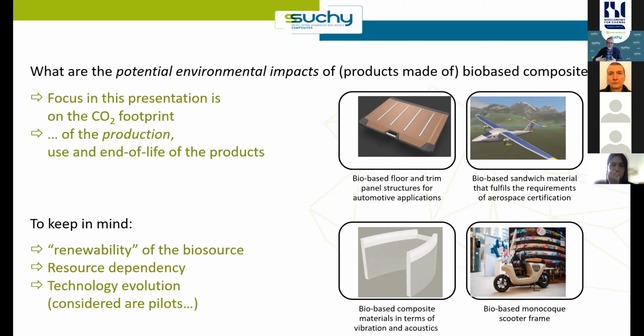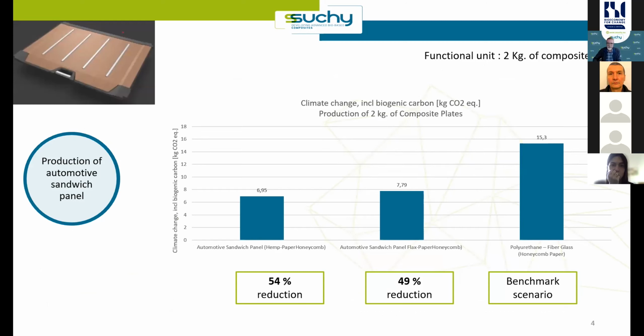And so you can foresee that there will be further technology evolution. So to come to the first demonstrator, the floor panel, which was actually the last presentation in the previous session, what we did see is, if we compare here at the right side with a benchmark scenario, the polyurethane with fiberglass reinforcements, that we can achieve with the SSUCHY solution about around 50% reduction for two different systems that we considered, the flax one and the hemp one of the SSUCHY project itself.